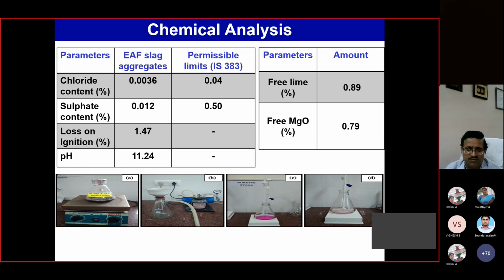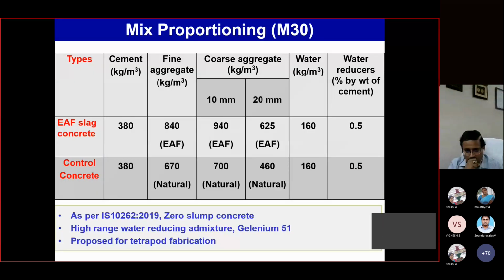We have done different processing of this aggregate by carbonation, by steam curing, by open natural weathering, and by microwave weathering. All of those worked and gave reductions, but we found that within 3 months it will reduce. And if you utilize it in concrete, the free lime is masked by the cementitious compound, so it is not going to have much effect on the concrete properties, that is, the expansive behavior is masked within the cementitious compound. That was the issue here.